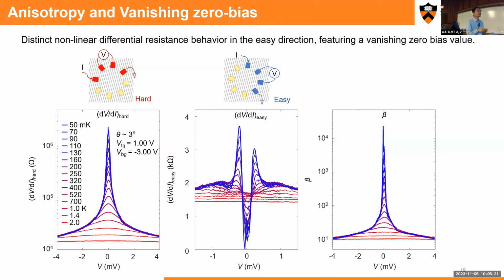And along another direction, it also shows a really strong contrast versus this easy direction. It shows a very, very high resistance. With external bias, you can just suppress it down.